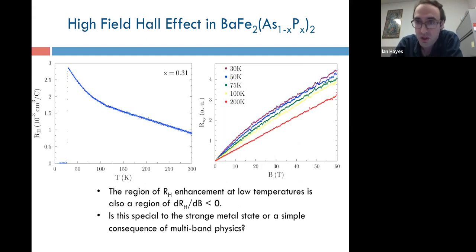So this has the makings of an interesting correlation between a particular field dependence, a decreasing RH with field, and the strange metal behavior in the temperature dependence, increase as you go to lower temperatures. And I will show you, based on where this particular field dependence lives in the phase diagram, that it's very unlikely to be a simple band structure effect. Probably is related to whatever scattering, whatever interactions are responsible for superconductivity. But as was mentioned many times in the previous discussion, barium-122 is a multi-band system, and so you can get both changes in RH with temperature and changes in RH with field in very simple multi-band physics.